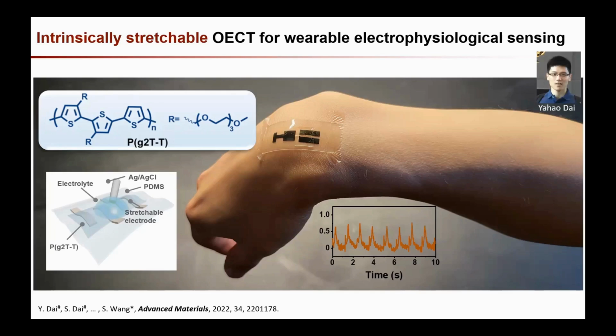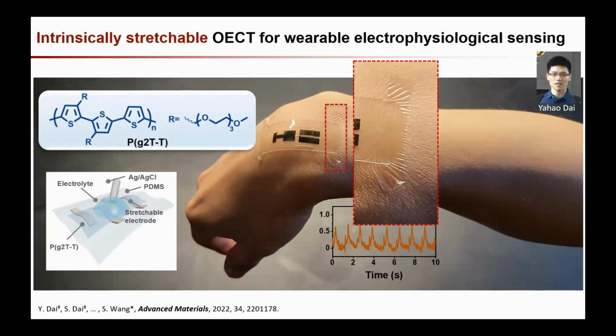But when I previously showed these results, people often ask me one question: how do you attach it? And honestly, we didn't use anything that is fancy or high tech. It's a very simple way to attach the device. I'm not sure if you can tell from the picture. If you cannot, I can further zoom in. So it's by using 2 pieces of tape at the 2 ends of the device. So this can work overall, but it's not optimal, because at the middle part of the device where the sensing really happens, you can probably see there's still a gap in between, right? It's because the device intrinsically doesn't have the adhesive property to the skin surface.